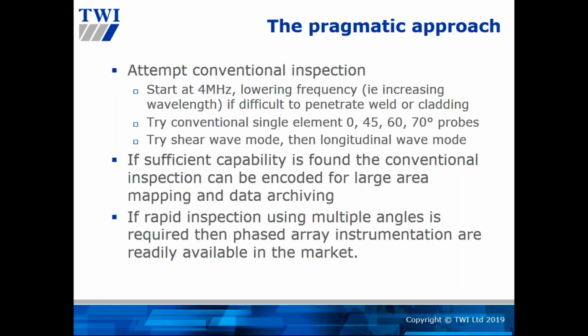So what we tend to do is say, okay, we start with a known typical frequency such as 4 megahertz, and then from there we lower the frequency in order to get sufficient signal-to-noise performance. We always try and work with single element probes, so conventional UT and the standard beam angles, wherever possible, because it's cheaper. But we also consider the use of shear wave, which is the standard weld testing wave mode. But then we move on to longitudinal wave mode because it gives a larger wavelength for the same frequency.